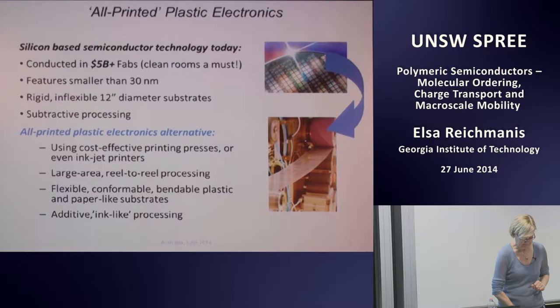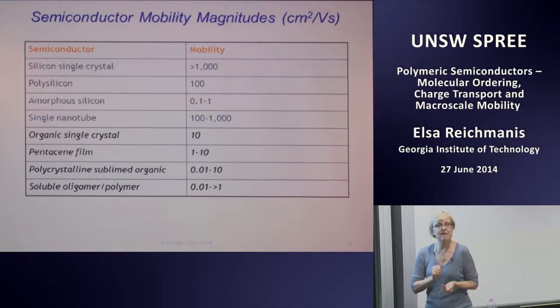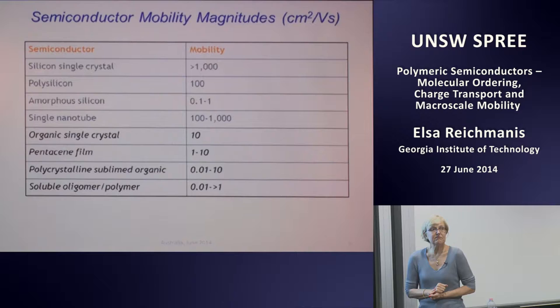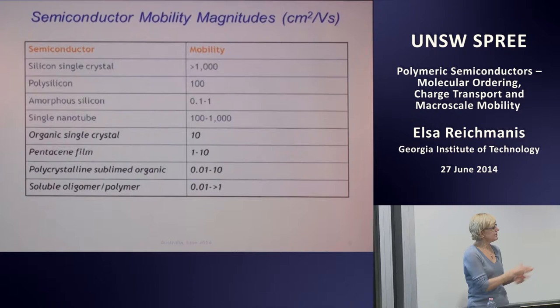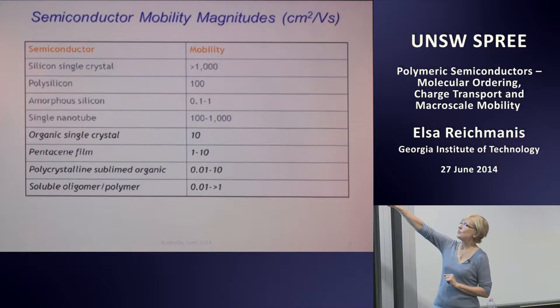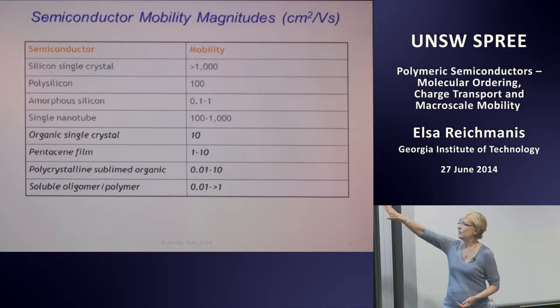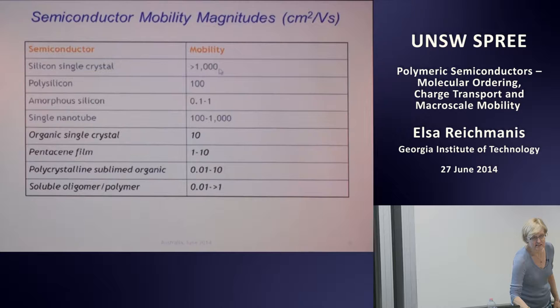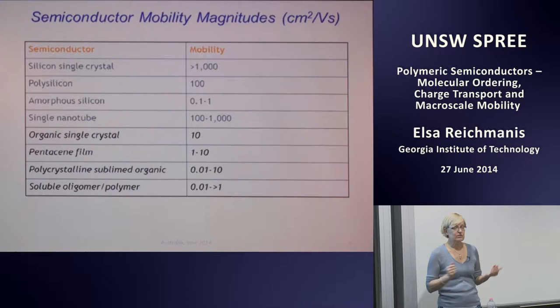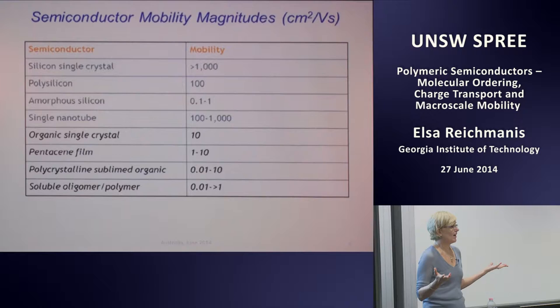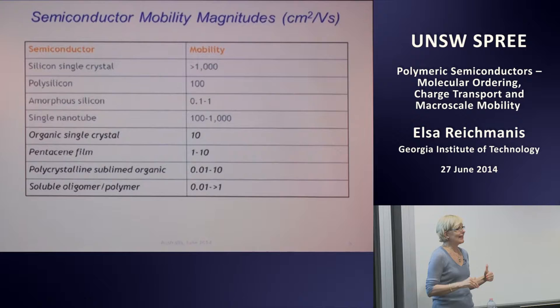All right, so if we think about the figure of merit for semiconductor materials, that's typically thought about in terms of how effectively charges transport through a thin film material, as measured in mobility, or centimeters squared per volt second. If we look at the mobility of single crystal silicon, it is greater than 1,000 centimeters squared per volt second. Are organic materials going to reach that? I suspect not. I don't see any way, at least in my lifetime and probably my children's and grandchildren's lifetimes, that organic or polymer materials are going to reach that level of performance.